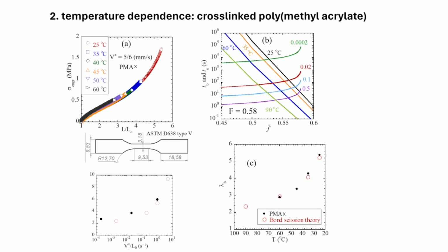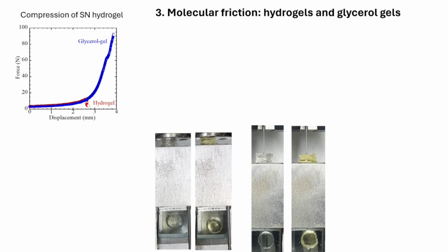So I'm almost done. So the third one is the most intriguing. In fact, I will probably agitate most people on this topic. Hydrogel. I had a feeling that this theory would even, I predict, if you change the water in your hydrogel with glycerol, whose viscosity is a factor of 1,000 times larger, this hydrogel will instantly become tougher.